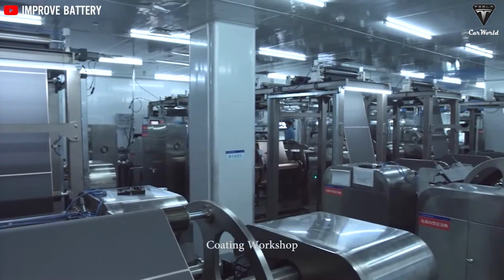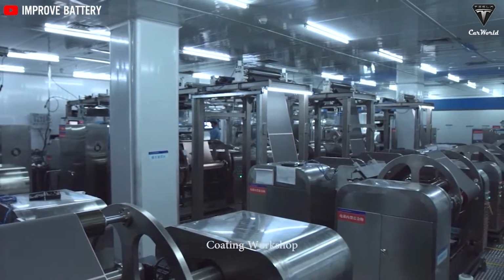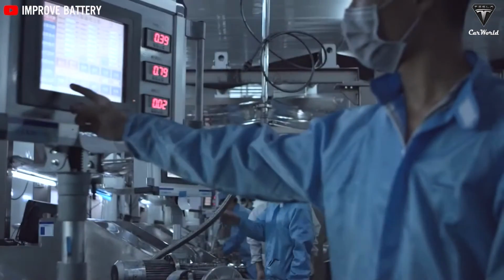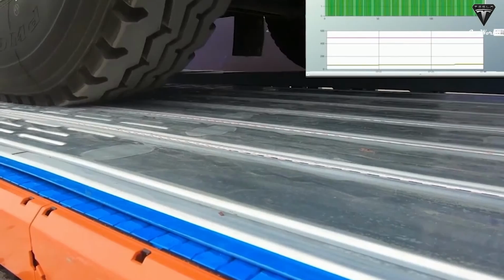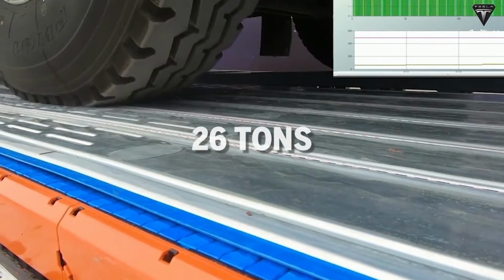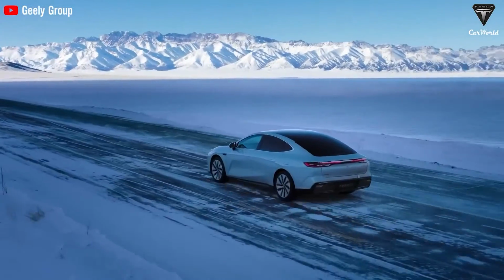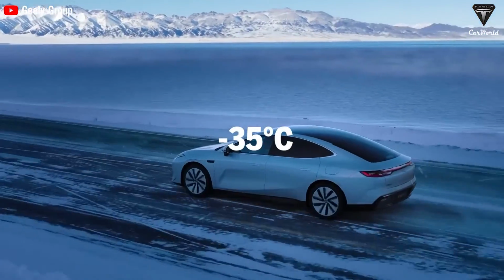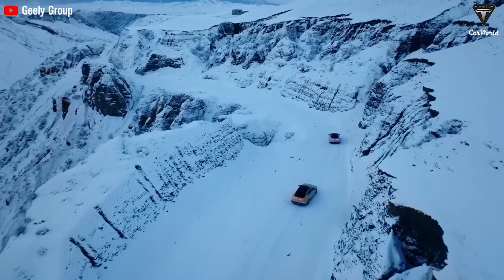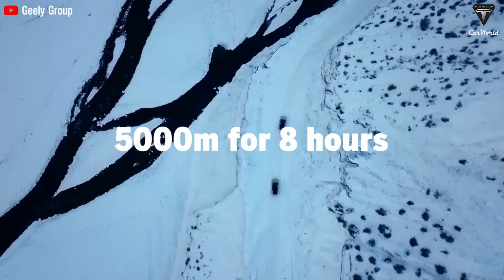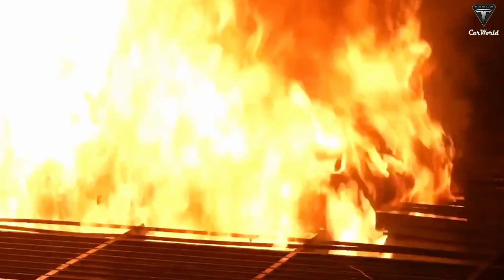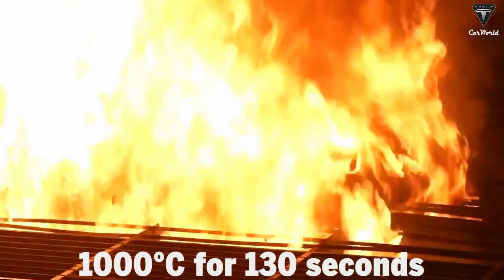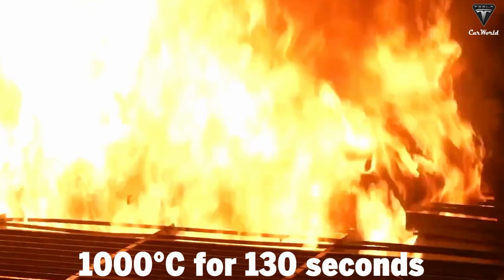These tests meet higher standards than national requirements, and in the scraping test, 3 repetitions were required. The rolling test endured a weight of 26 tons. The cold weather test withstood minus 35 degrees Celsius at an altitude equal to 5,000 meters for 8 hours, and the fire test endured 1,000 degrees Celsius for 130 seconds.